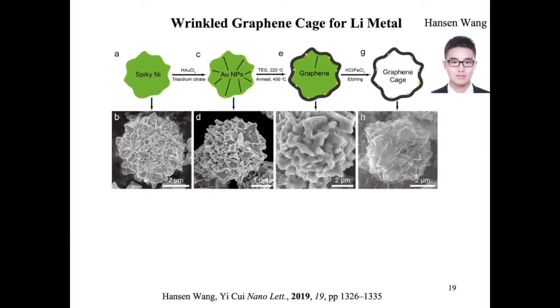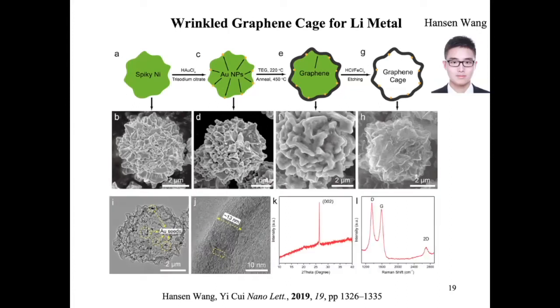We have this amorphous carbon with slightly graphitic domain right there. We found out those are mechanically not strong enough. That's why understanding the materials properly is super important. And if we could grow highly graphitic carbon, using some of these catalysts, for example, having a nickel coating right there, you could grow this graphitic carbon and later dissolve away the nickel inside, and you can produce this graphene cage. A gold seed in there is the nucleation location. This indeed improves the performance quite a bit, and the electrode becomes a lot more resilient mechanically if you put mechanical force on it. So we saw the improvement like that.